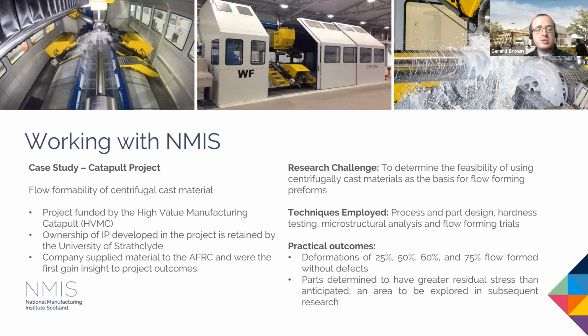The research challenge for this project was to determine the feasibility of using centrifugally cast materials as a basis for flow-forming preforms. The idea behind this was to reduce the material wastage from machining a preform, but also to get the benefits of centrifugal casting, such that you get a forged-like microstructure, and you're able to tailor the cast as well to suit specific properties if required. The techniques employed in this project from NMIS: we carried out some process and part design to identify a suitable